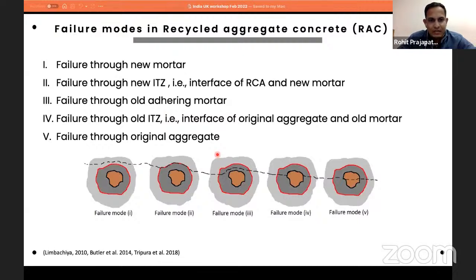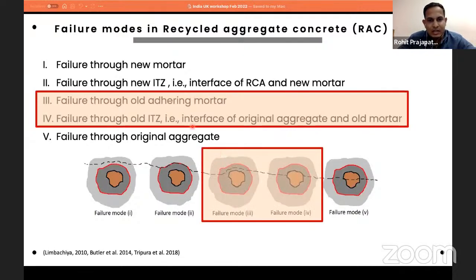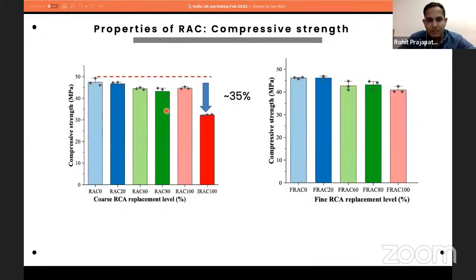Since we have removed this adhered mortar, these 2 failure modes were eliminated. Now let us see the effect of this beneficiation on the concrete properties. So we have 2 series of concrete. In the first RAC, we have volumetrically replaced the coarse pristine aggregate with the beneficiated aggregates, and in the second one we have replaced only fine aggregate.